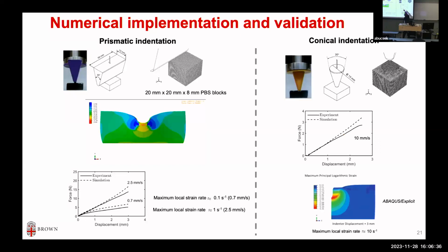We went ahead and did another kind of simulation. So this is a cone, like an axisymmetric kind of simulation. It's a full 3D simulation, but the geometry of the cone is axisymmetric. We again deformed it, measured the force, and compared against the simulations. We can predict. So this is an example of validation of a model that was calibrated against 1D, but it has full 3D predictive capability. So I'll stop about this rate-dependent gel. A very quick summary of what we did. The paper got published a few months ago, so if you're interested, you can read it.